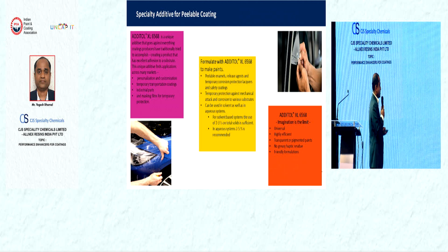It has no greasy or haptic residue after the peeling of the film. With temporary protection coatings, or coatings applied on appliances in transportation, there are chances of damage to the base substrate. So to avoid mechanical damage to the base substrate, these temporary protection coatings are recommended. And to achieve that temporary protection performance, this additive works very well.